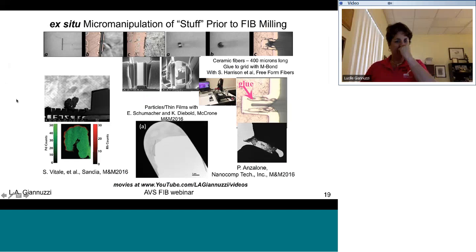Okay, so I mentioned earlier that a better way to manipulate samples, you can do it by hand, but a much easier way is to use ex situ micromanipulation, which I'll talk about in a little bit. This is a way that you can manipulate small particles, fibers, particulates, thin films to grids prior to FIB milling. So this is actually a longitudinal and a transverse cross-section of small fibers. And even for carbon nanotubes, obviously you're not going to FIB mill carbon nanotubes, but it's just a way to easily manipulate samples. If you want to see those examples, you can look at my YouTube page for lots of examples.